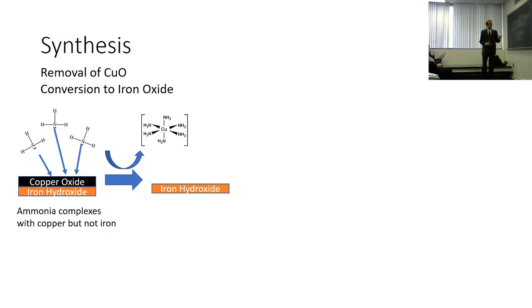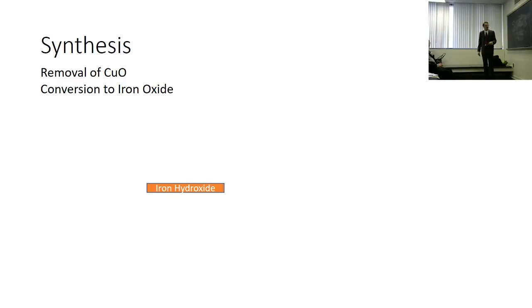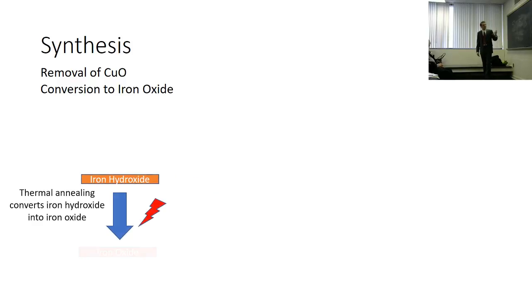Makes a nice blue solution. So if I rinsed my mixture in ammonium hydroxide, got the nice blue color, and was left only with my iron hydroxide, I could heat it up to iron oxide. Hematite's the most stable form of iron oxide. It's pretty easy to get if you just heat it in air or oxygen. Short time though, you don't want to kill the structure.